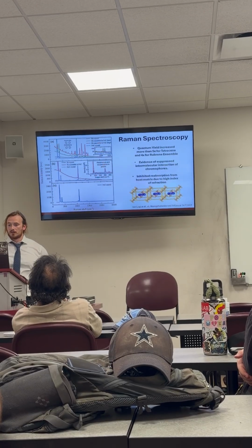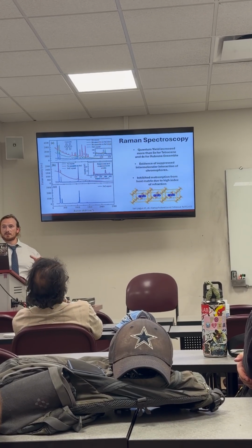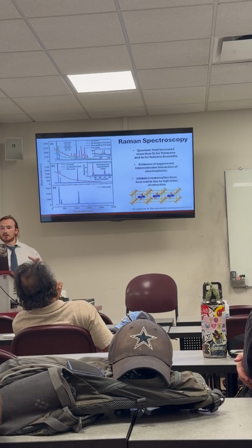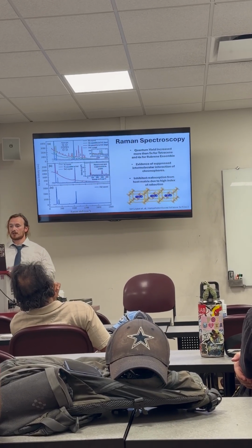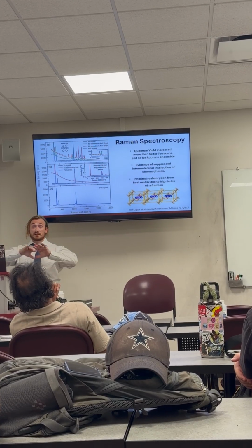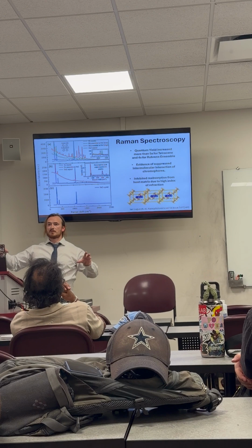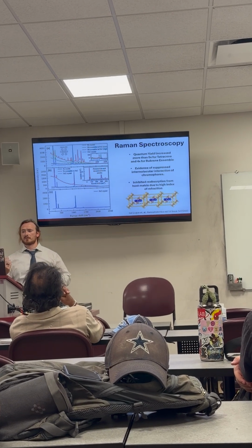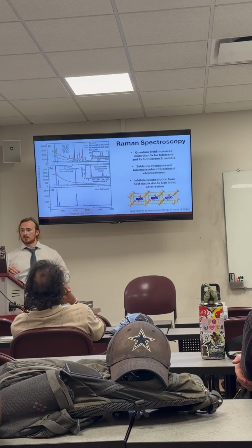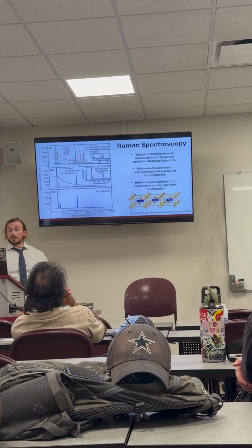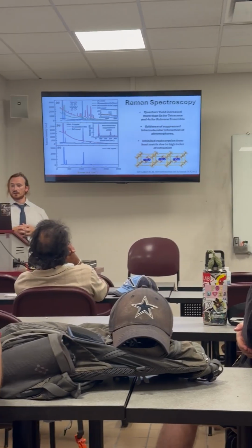Now, the reason for this enhancement of the background Raman emission is that when the chromophore is doped inside that host matrix, it's separated from other chromophore neighbors. So it becomes more monomeric in nature. Monomeric meaning it's acting like an individual molecule that's not interacting with its neighbor. Fluorescence also, due to the color that we were talking about earlier.